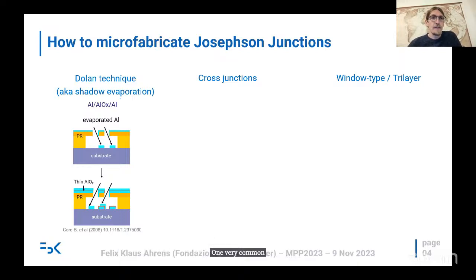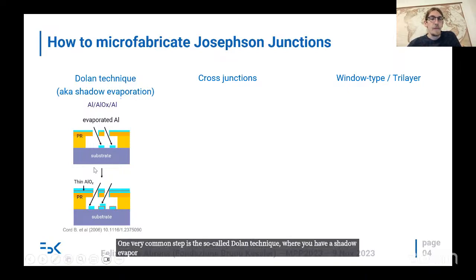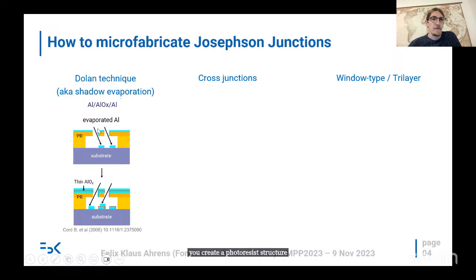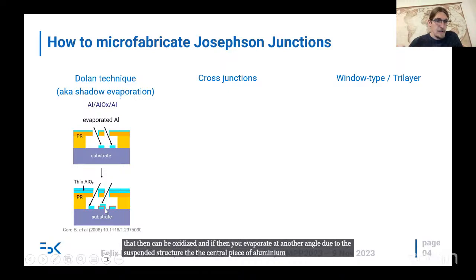One very common technique is the so-called Dolan technique, where you have a shadow evaporation technique. You create a photoresist structure which has some sort of bridge or some structure which is suspended above the substrate. So you will notice that if you evaporate aluminium at a certain angle through this double slit here, you will get two pieces of aluminium that then can be oxidized. And if then you evaporate at another angle, due to the suspended structure, the central piece of aluminium that is oxidized will have now a second piece of aluminium on top, and having two aluminium pieces on top of each other with a small layer of oxide in between is just a Josephson junction.